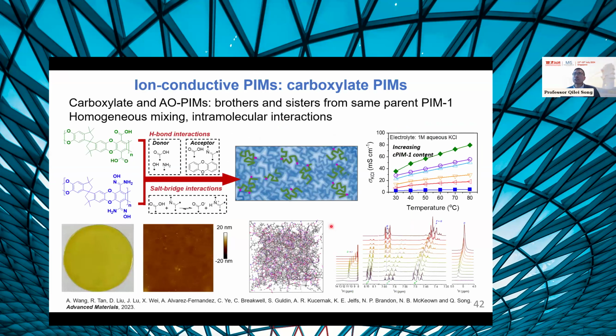So then we realized we could combine the carboxylate PIMs with the amidoxime PIMs because they derive from the same parent. It's kind of like their brothers and sisters. They have a really good relationship. So when you mix them together, you get hydrogen bonding, homogeneous dispersion, and also very good interactions. Because this carboxylic acid can easily dissociate, we got much higher ion conductivity.